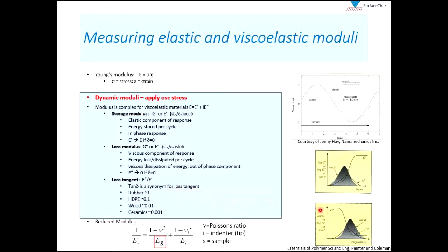And here you can see, again on the right, some plots of the storage modulus, the loss modulus, and loss tangent as a function of frequency and as a function of temperature. And you can see the loss tangent, again, just being the ratio of the two. The reason we like that one is that there are peaks in the loss tangent when you collect it as a function of frequency and temperature. And those peaks pinpoint thermal and structural transitions in our material. So that's very useful information.